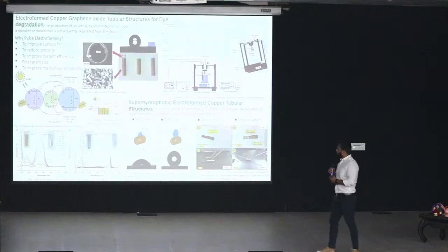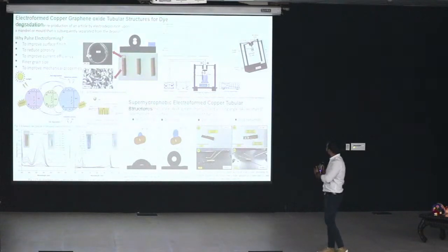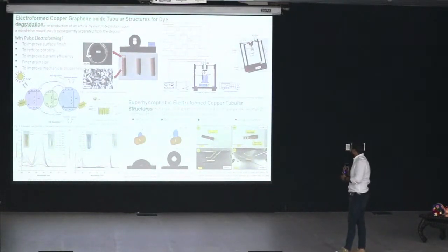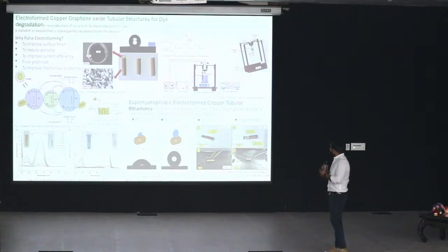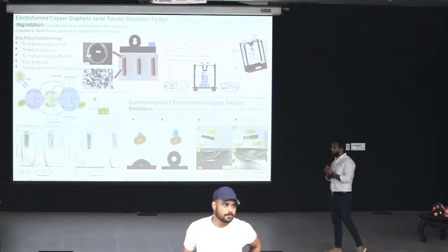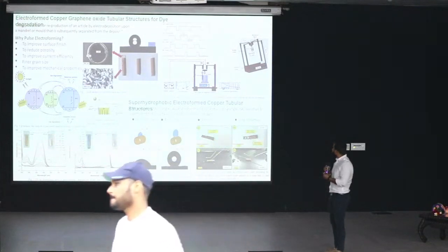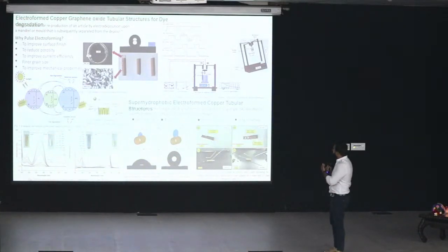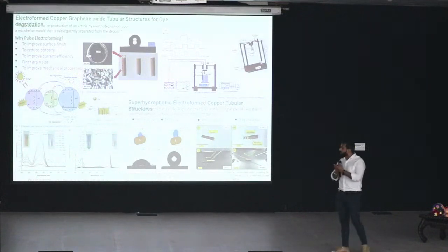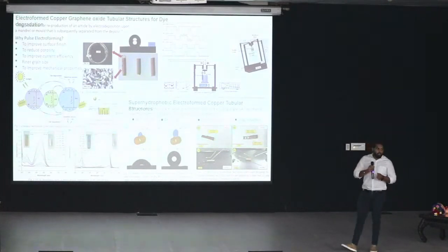In this work, we aim to produce miniaturized products of various shapes and sizes using this electroforming process, using this in-house pulse electroforming setup. The setup includes a function generator and oscilloscope, which is used for providing a pulse waveform instead of a direct current waveform. And we have used a power supply to give rotational movement to the cathode during the electrodeposition process. And using this in-house pulse electroforming setup, we have fabricated some metallic microtubes of copper and copper graphene oxide of 1 mm internal diameter and having wall thickness of 20 to 80 micron.